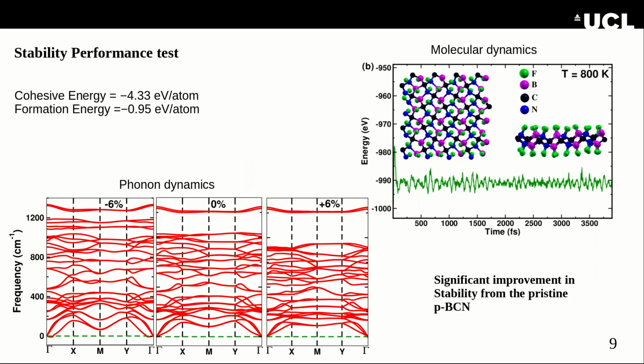Further, we checked the stability, and we found that the material now exhibits negative formation energy and cohesive energy, which indicates that the fluorinated BCN is chemically stable. Further, we performed molecular dynamics simulation using an NVT ensemble up to a time of 3500 femtoseconds, and we found that the geometry is stable without any destruction or bond breaking. And further, we confirmed the dynamic stability by performing the phonon calculation, with non-imaginary bands in the phonon diagrams, so that the compound is dynamically stable, which is lacking in the pristine form.